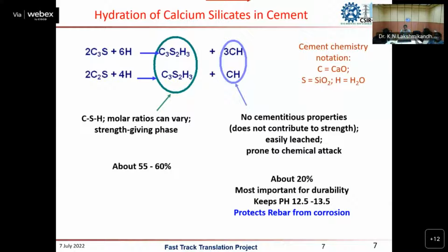Another thing we want to utilize is industrial waste like GGBS or fly ash. This is the basic chemistry behind the process of concreting. There will be a CSH gel forming when we add water to cement, and about 20 to 25% of calcium hydroxide remains idle in the concreting process. Actually, this is very good in terms of durability.